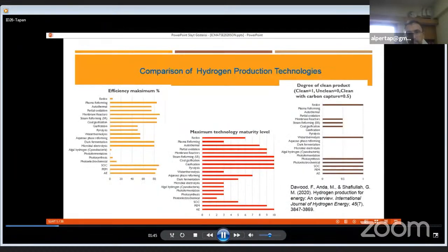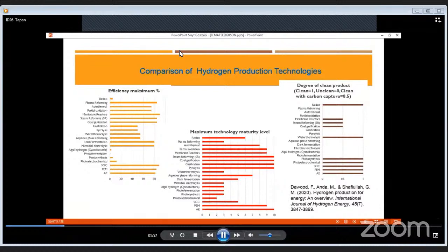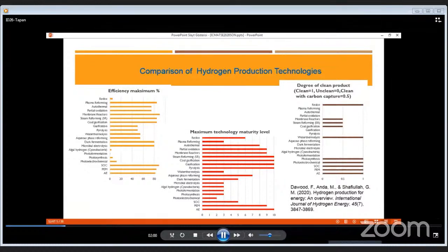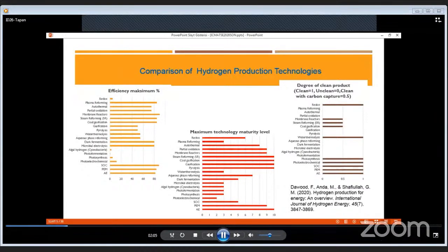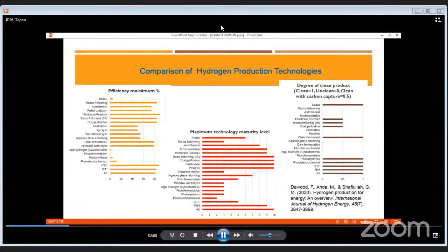Here this slide gives a good comparison of the state of different hydrogen production routes. It's seen that electrolyzers have both high efficiencies and clean production routes, and especially low temperature electrolyzers have a high technology maturity level. Although high technology maturity levels are seen for electrolyzers, and although high current efficiencies were observed like 67 to 74%, there are research and development efforts seen for alkaline electrolyzers, especially on catalyst, membrane and efficiency.